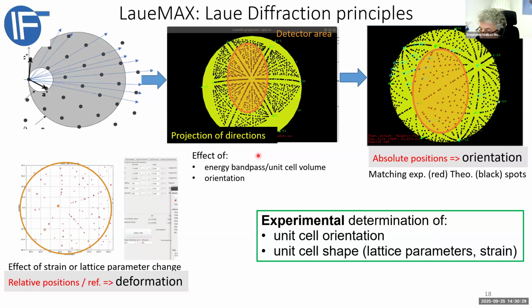So Laue diffraction is different from monochromatic diffraction. Simply, in one shot you can do the reciprocal space map, but there is no free lunch. Actually, this is a particular reciprocal space map. You are making the map of the directions of the reciprocal space. So each point there, and these black points will be the spots we can see in the Laue pattern, corresponds to a direction in the reciprocal space.